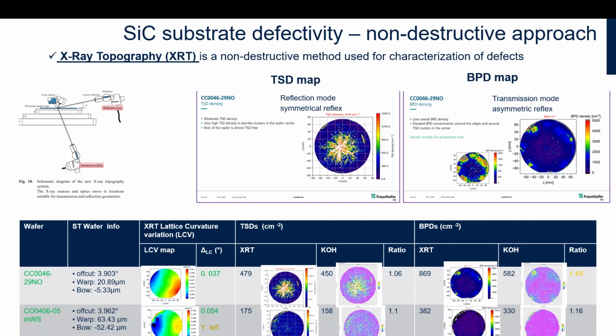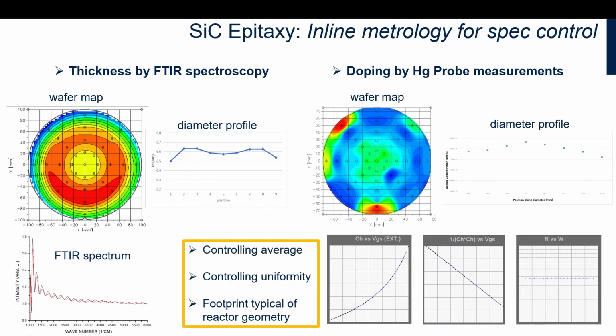And then if you go to epitaxy, you now grow a layer on top of the silicon carbide, and you make some transformation of the defects. Again, you have to measure, of course, the thickness, because in a power device, the thickness and the resistivity of the epi layer basically determine the voltage class. You have to measure the thickness, you have to measure the doping, and we have to take into account the uniformity of the doping, which is another point to take into account.